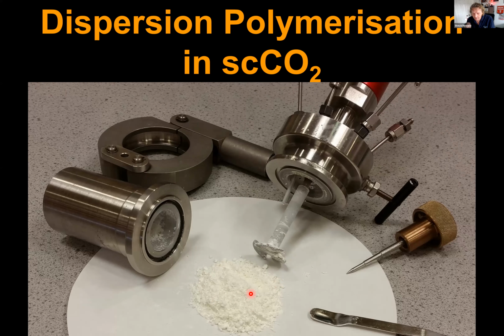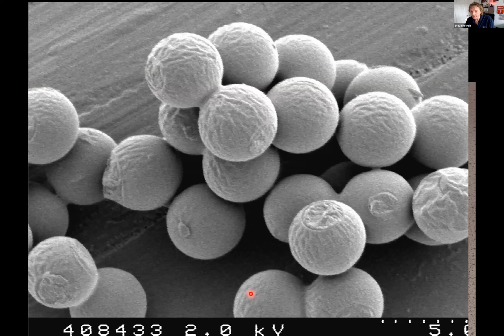But when we focus into this material using the electron microscope, this is what we see. So those particles that were stabilized by the detergent, you can see come out as particles and really quite nicely. These have a diameter of around about 3 microns very effectively. And so this is stuff we were doing way back now, probably 20 years ago when we first began this work and we started to understand how to do dispersion polymerization.